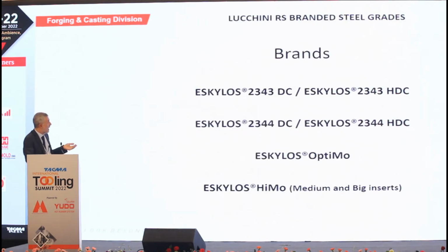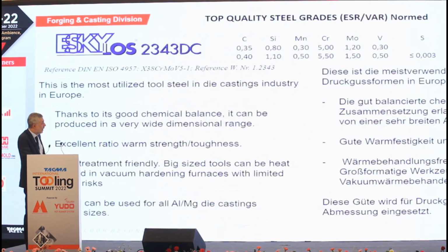Some information about the brands now. 2343, 2344, Eskylos Optimo, Eskylos HiMo, all in ESR. So 2343 is the most utilized tool steel in die casting industry in Europe. Very good chemical balance, so it can be produced in a very wide dimensional range. Excellent ratio of warm strength and toughness, and is quite heat treatment friendly. So big size tools can be heat treated in vacuum hardening furnaces with limited crack risk. So this steel can be used for all aluminium magnesium die casting dies in all sizes.